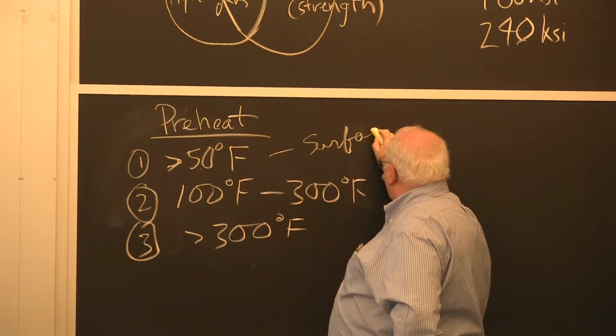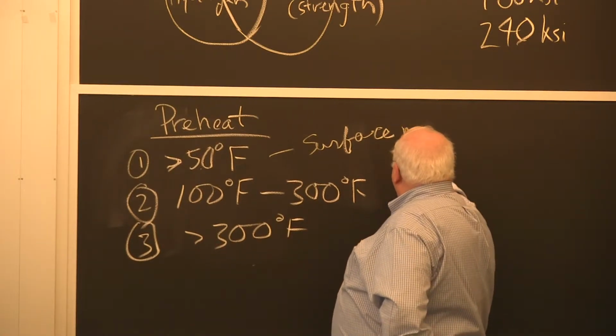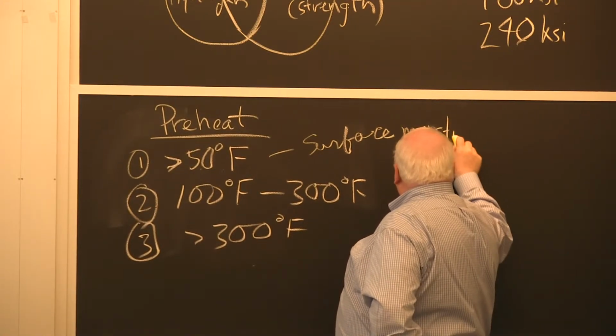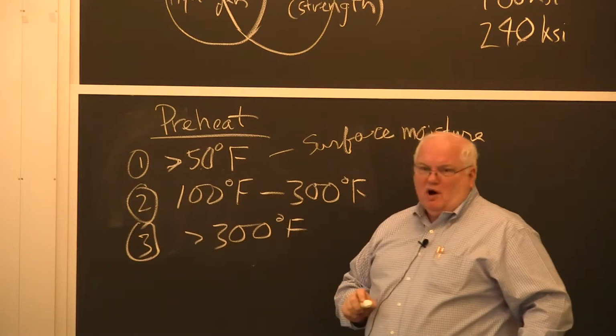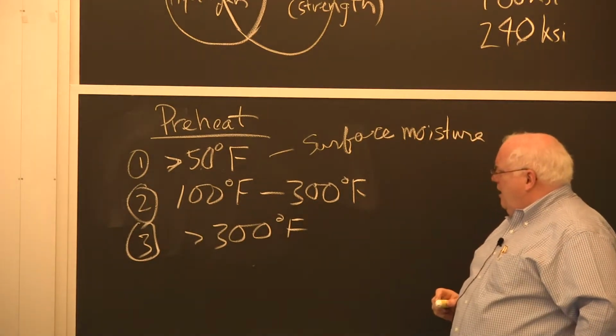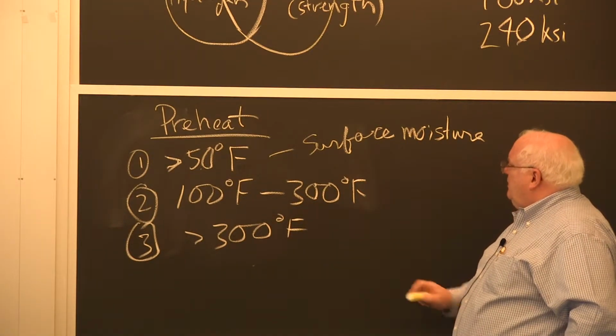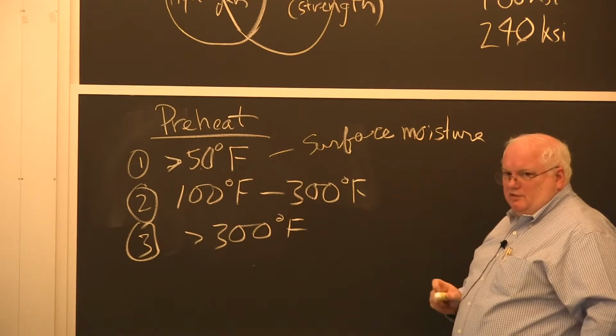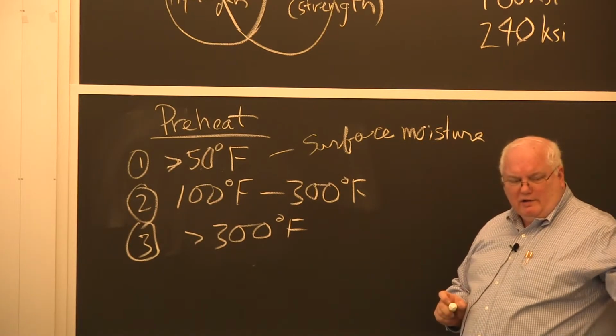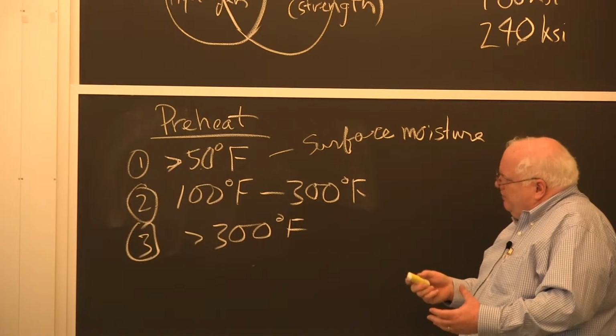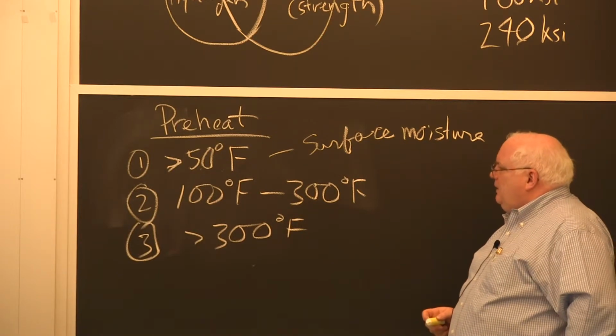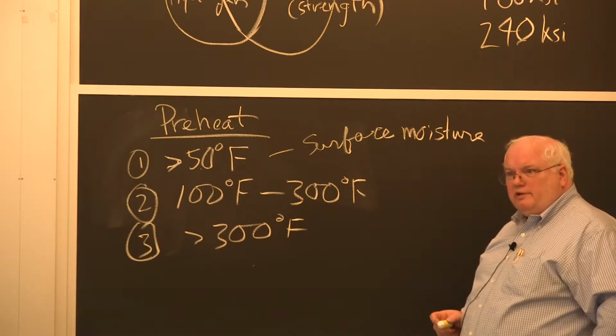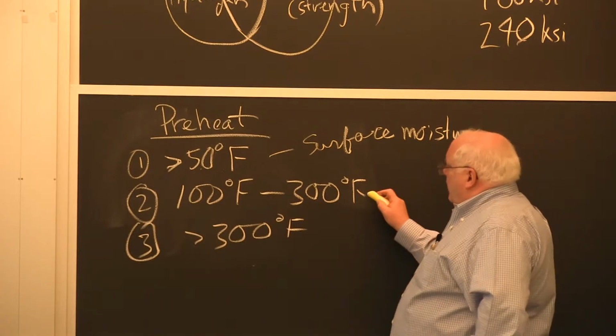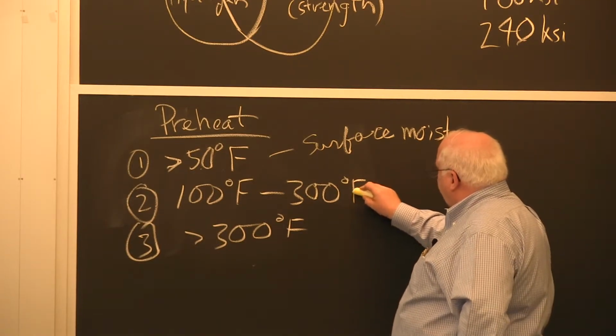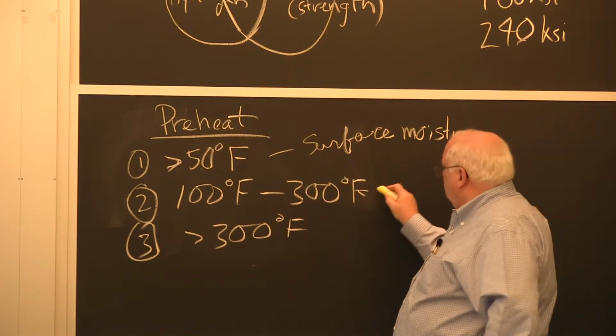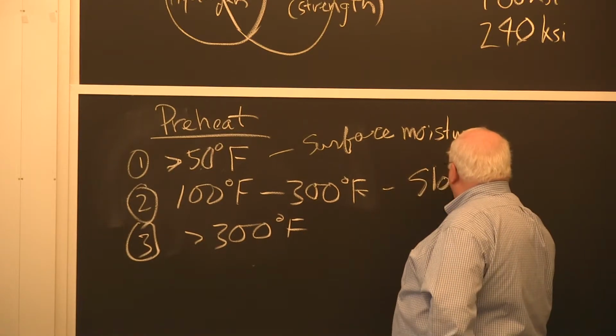You've got to drive off surface moisture, no matter how mild the steel is, no matter how low the carbon is, no matter how low the hardenability of the steel is. You still got to get rid of that surface moisture, and that's why the 2 codes say 32 degrees, 50 degrees, whatever. You don't weld on snow, under snow. Okay, 100 to 300 degrees F. What am I doing? I'm slowing the cooling rate.